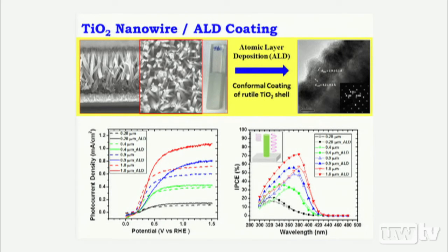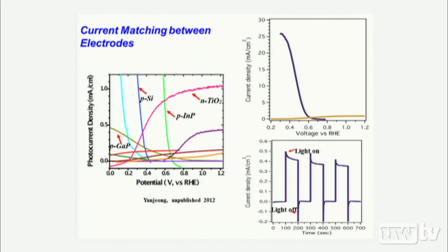We're developing a hydrothermal process to make the TiO2 nanowire array. Right now, even though they are a UV material, these TiO2 nanowires can still give us more than 1 milliamp per square centimeter. And it's a UV material, so that's the limiting factor here.